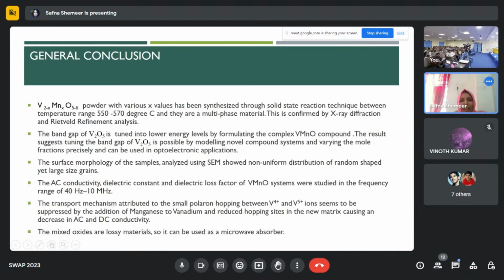The surface morphology analyzed using SEM shows non-uniform distribution of shaped yet large grains. The AC conductivity, dielectric constant, and dielectric loss factor of the VMNO system were studied in the frequency range of 40 Hz to 10 MHz. The transport mechanism attributed to the small polaron hopping between V4+ and V5+ ions seems to be suppressed by the addition of manganese to vanadium and reduced hopping sites in the new matrix, causing a decrease in AC and DC conductivity. So the mixed oxides are lossy material, so it can be used as a microwave absorber.